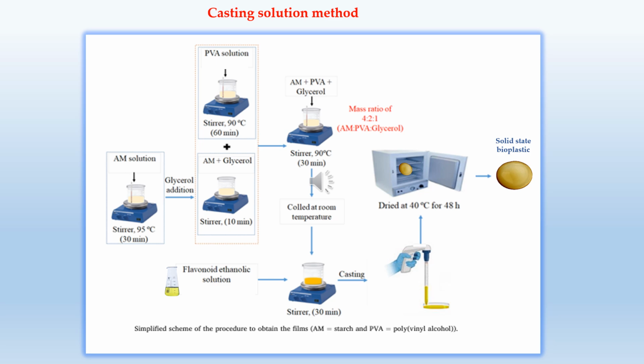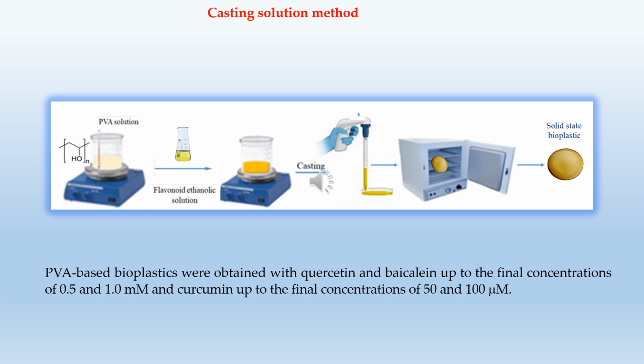Subsequently, 3 separate solutions of quercetin, curcumin, and baicalein at various percentages were added for each bioplastic. Finally, 10.0 milliliters of each prepared solution was placed in a petri dish and left to dry for about 2 to 3 days. In bioplastics containing only PVA and flavonoids, the procedure is the same, obviously without the steps where starch and glycerol are added. In this way, PVA-based bioplastics were obtained with quercetin and baicalein up to the final concentrations of 0.5 and 1.0 millimolars and curcumin up to the final concentrations of 50 and 100 micromolars.